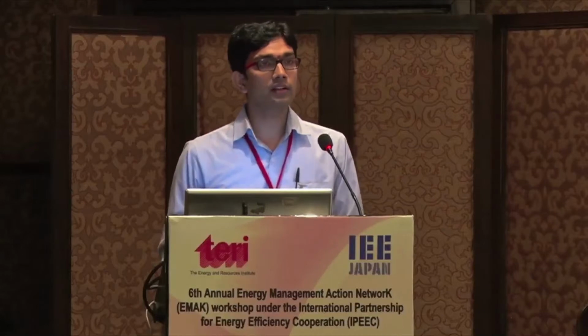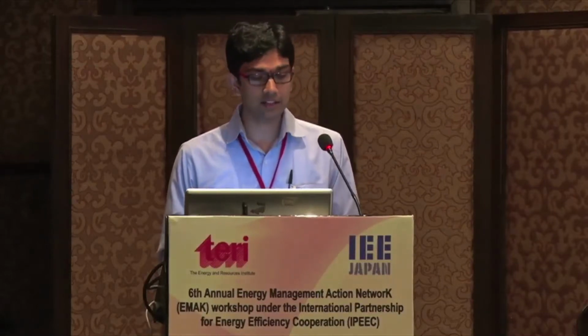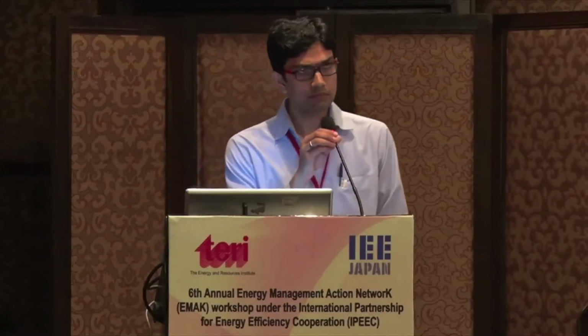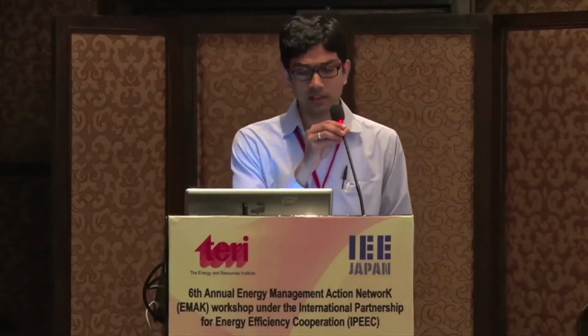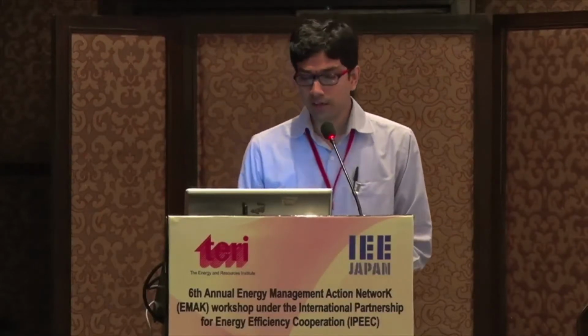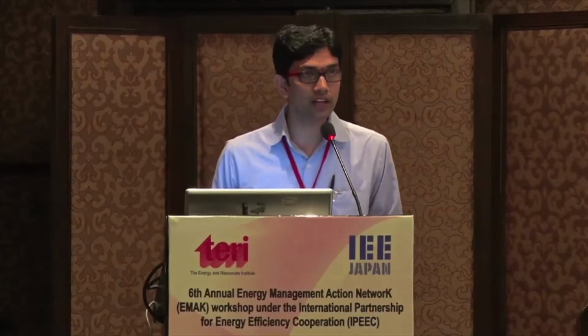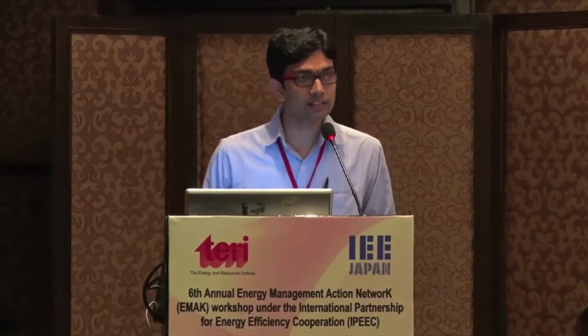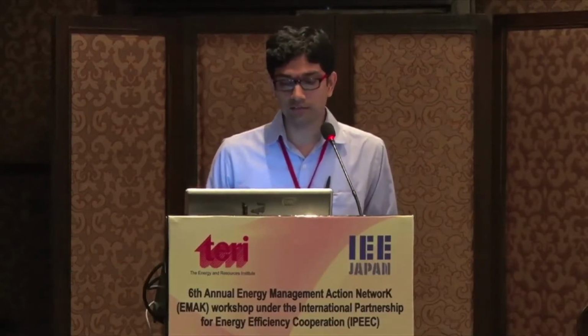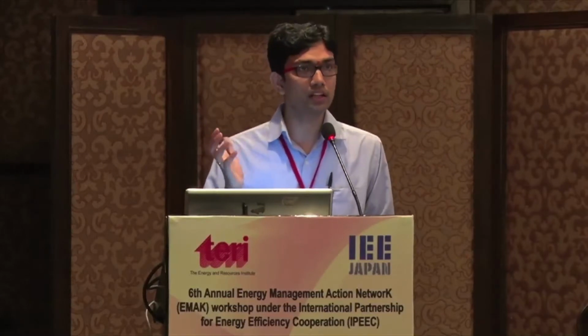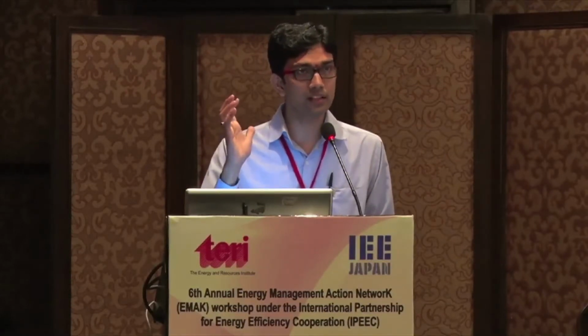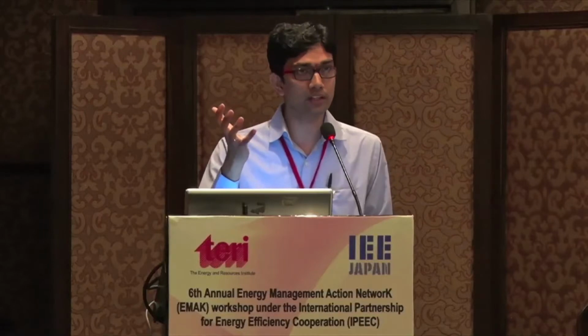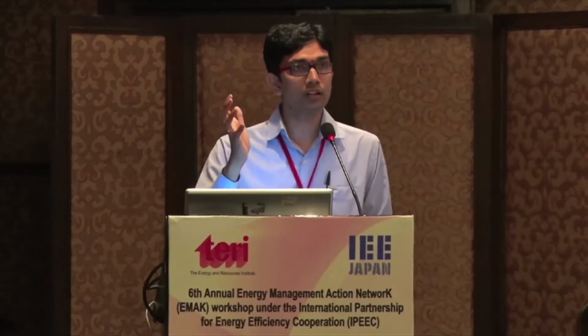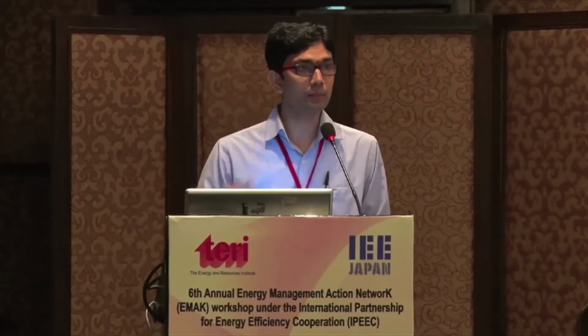However, having recommended this excess air control in Faridabad, in many of these forging sector units, we found that the receptiveness is not very high. The reason behind this is that the SME units actually don't understand reduction of air going in. They understand more in terms of temperature, reduction of temperature.